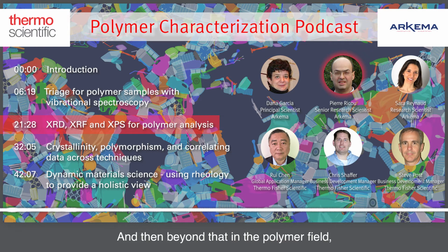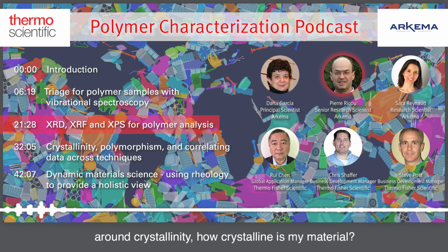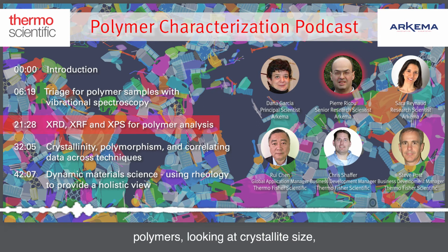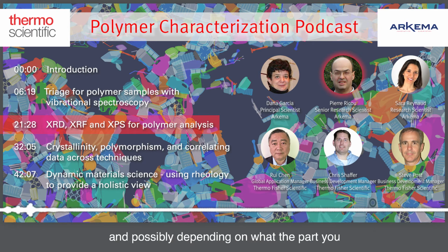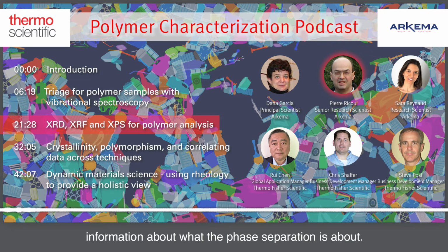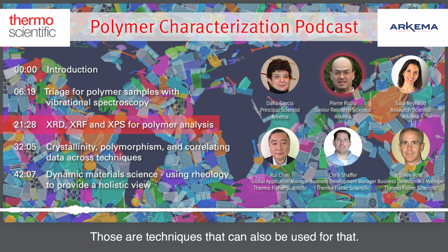And then beyond that, in the polymer field, so looking at what crystal phase you have, the big question is usually around crystallinity: how crystalline is my material? So you're talking semi-crystalline polymer, looking at crystallite size, and possibly, depending on the part you receive, could it have some orientation? Or, as was mentioned with the vibrational technique, you can also do micro diffraction. So looking at small defects in your material and trying to identify them, or a possible phase blend that has somewhat phase separated. And if you want to get a little more information about what the phase separation is about, those are techniques that can also be used for that.